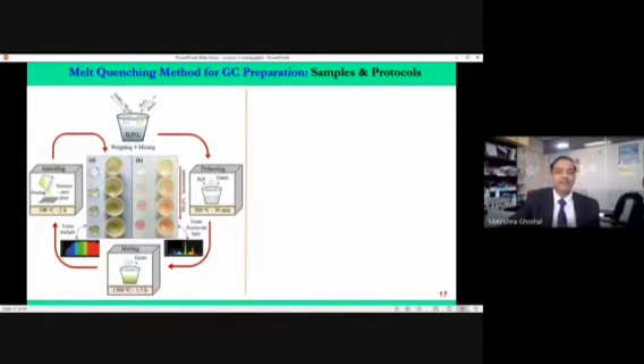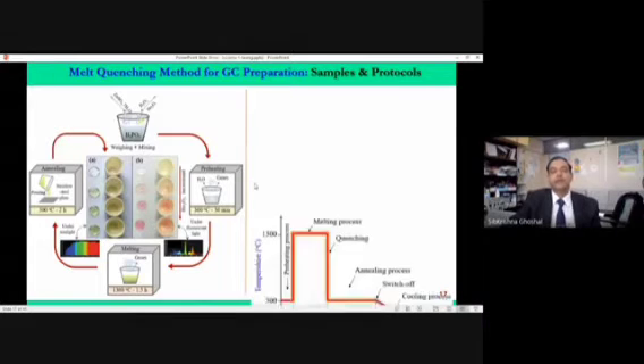So here I have explained how we start from the raw material, then put it in the furnace, grind it, melt it, weigh it, and then in the furnace we put in the porcelain, the platinum, the alumina crucible to get the kind of material. This left hand side is showing the material without rare earth doping, right hand side is showing the material with rare earth doping. That's why the color changes, and this is the way we get it.